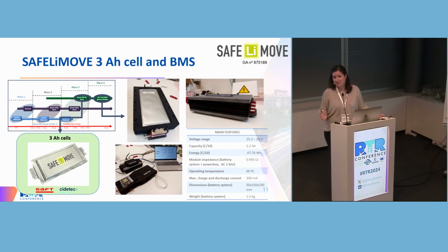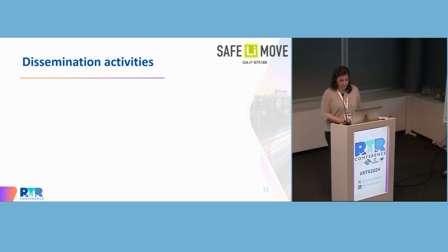However, by means of the energy density, we were not able to meet it, mainly because you can consider that we are talking about cells with 3 ampere hours. So this means that the weight and the volume of the module is impacting a lot on this. So we were not able to reach these KPIs, but at least we were able to prove that the module that was developed was working as well, also by means of safety, the parameters related to overheating, over voltage or over current. So this was the last milestone of the project. And then I will be brief on this part. So there are also other activities that have been performed.